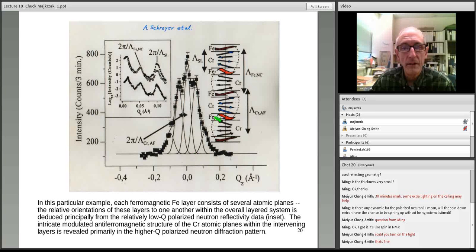It's so-called giant magnetoresistance effects, where you can get ferromagnetic layers of iron, for example, to line up parallel or anti-parallel depending on the magnetic field applied across an intervening layer of, let's say, chromium, which is an anti-ferromagnetic spin density wave. But the mechanism for this coupling by long-range indirect exchange interaction was actually determined by neutron scattering studies.